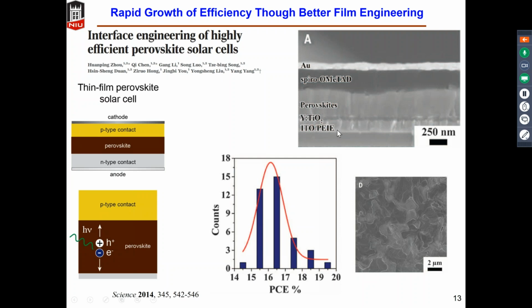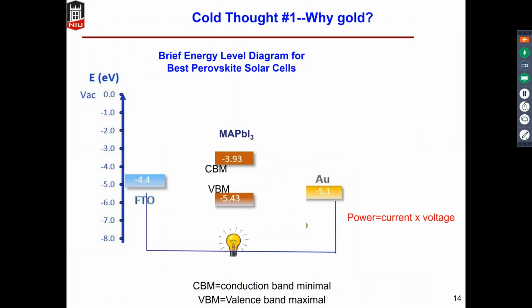But the trick here is that you have to make a very smooth film with a large domain size in the film. And another trick is that for most of the champion cells, you have to use gold as the counter electrode or the cathode. The reason why so far the champion cells all use gold as the electrode will have to be traced back to the band structure or the energy diagrams of this MAPbI3, the classical hybrid perovskite material.